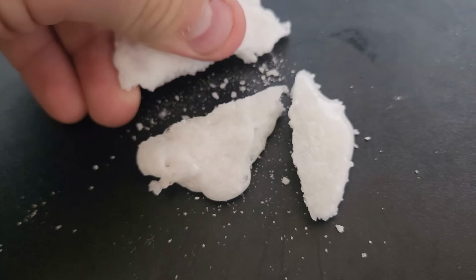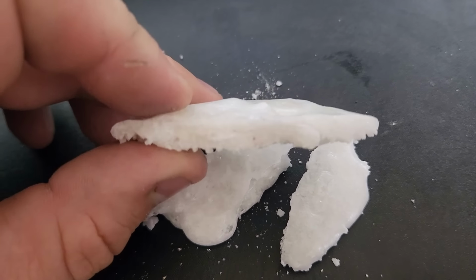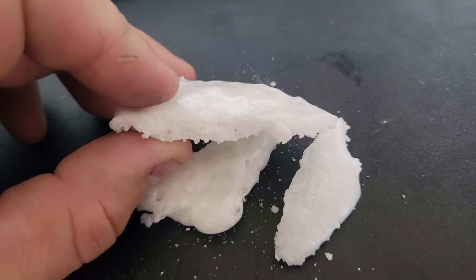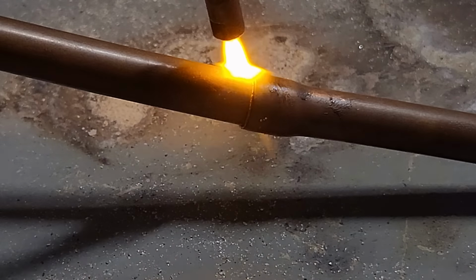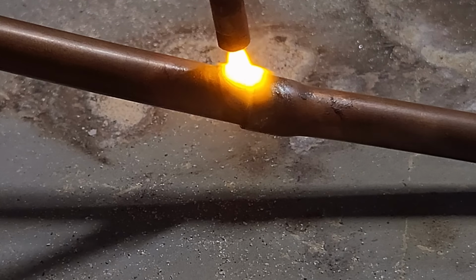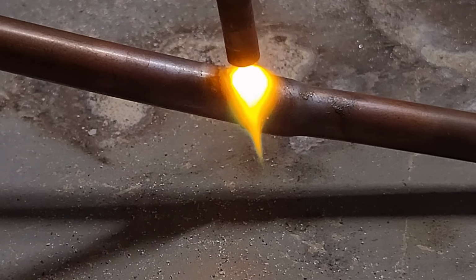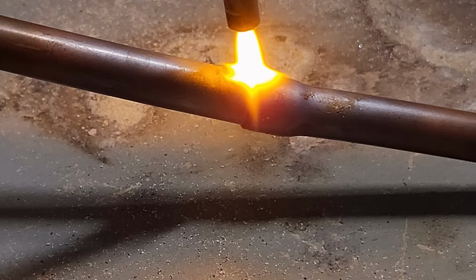When I was done, I ended up with a giant salt crystal. I even taste tested it and it was still pretty good. The flame actually works really well for brazing copper. The heating power is lower than that of a blowtorch, but because of the higher temperature, in a small area like a tube joint, it heats up quite a bit faster.